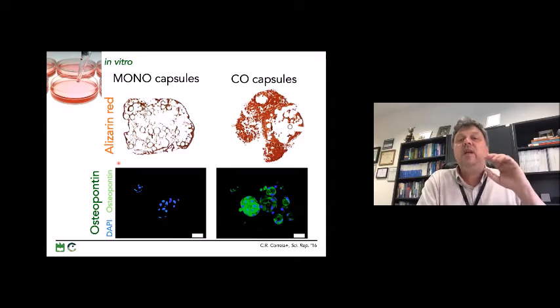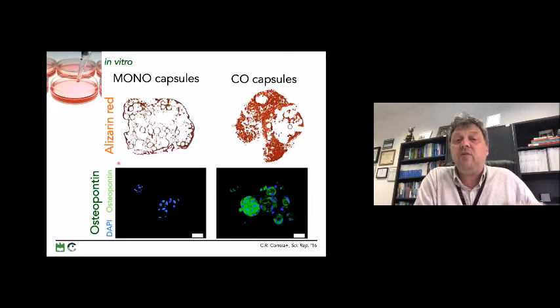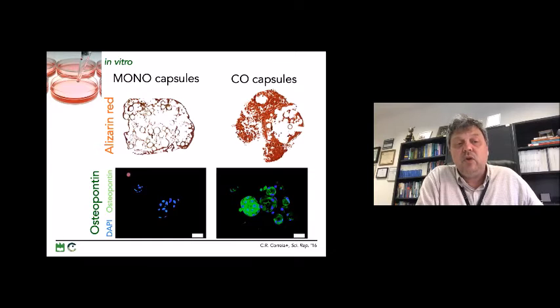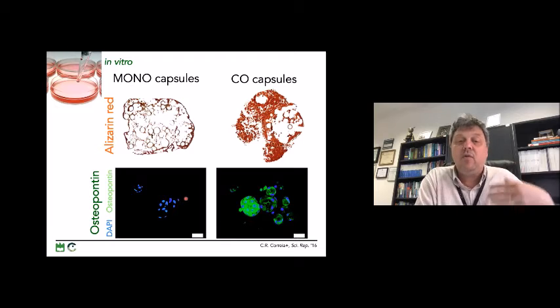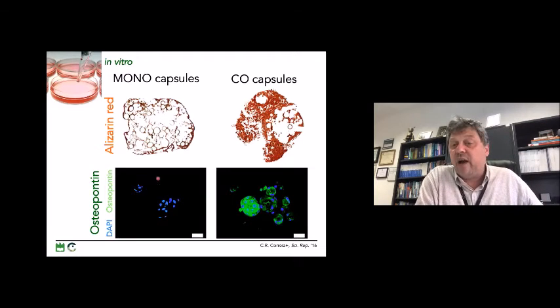So the definition of the initial cells that are already inside the capsules is very relevant for the type of tissues that we want to form without the intervention of any external factors, such as differentiation medium. So we would like to avoid that. For example, if we include just human-derived stem cells together with particles that were coated with collagen type 1 and culture the capsules in normal medium for 21 days, we could not see any development of mineralization. So in these kinds of monocultures, as you can see, we don't see any red staining in this alizarin red staining, nor the presence of osteopontin. So in here, you don't see any green, and osteopontin is really a sign of osteogenic differentiation. So the cells were kept viable, but maintained the stemness. So we still have stem cells after 21 days.